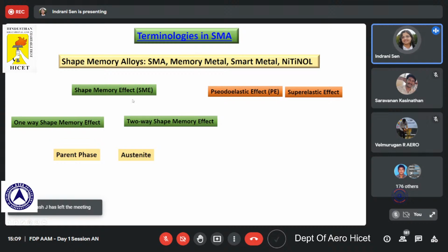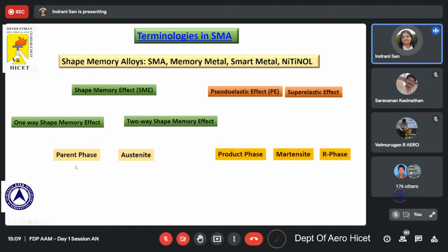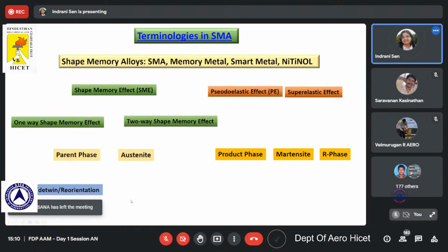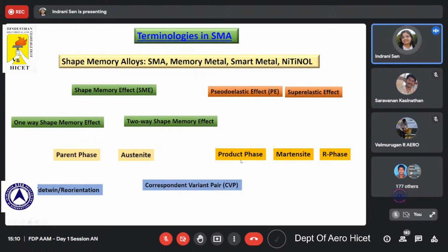Now all these effects, shape memory effects or pseudo-elastic effects, are related to the phase transformation. In any kind of phase transformation, there is a parent phase, which is the austenite, and a product phase or daughter phase, which is martensite, and the R phase is another intermediate phase. And then there is twinning, detwinning, or reorientation, which also happens, particularly in the martensite structures. The phase transformation from austenite to martensite, or parent to product, occurs along certain pairs of variants, called correspondent variant pairs, and a habit plane. I will explain this in a bit.